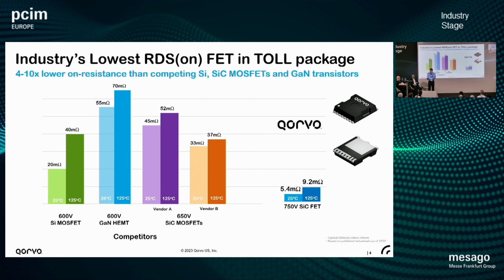So lately, I think at APEC, we launched some of our TO leadless package-based 750 volt devices. And you can see that the state-of-the-art device now achieves a resistance as low as 5.4 milliohm at room temperature, 9.2 milliohm at 125C. That package is, I think, 10 by 12 millimeters in size. So it's very useful for certain applications. And the rest of it is just us showing off that it's the lowest resistance device compared to our competition.